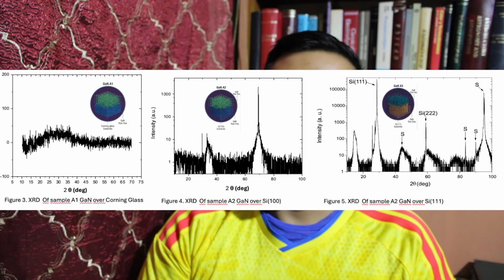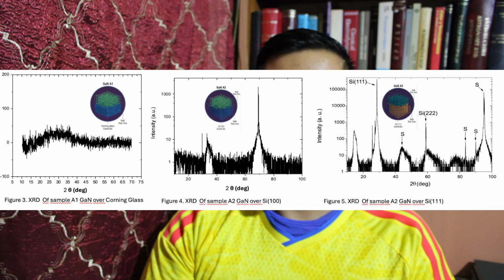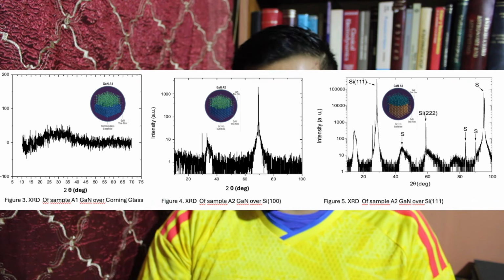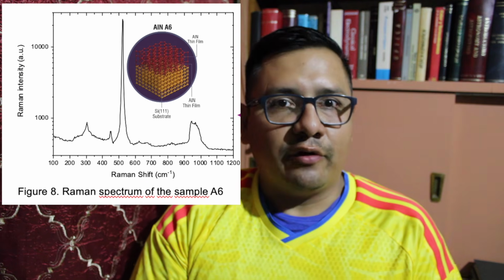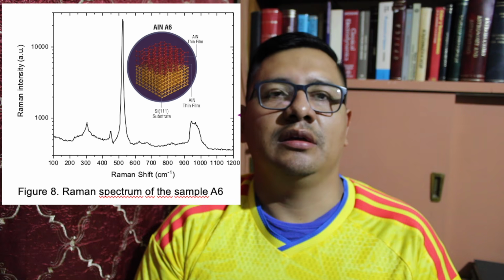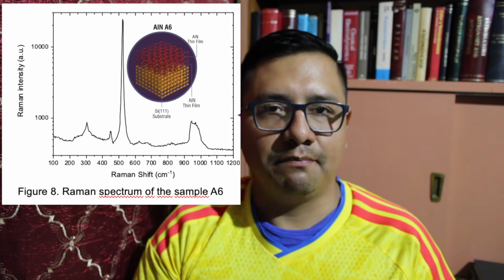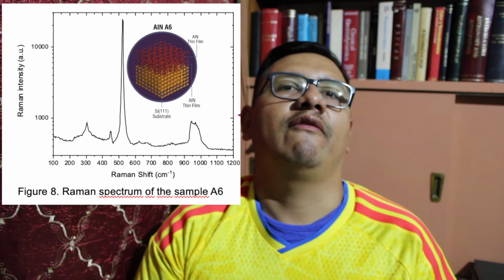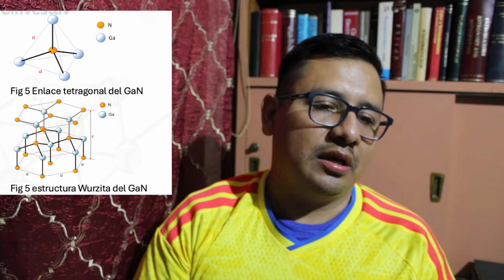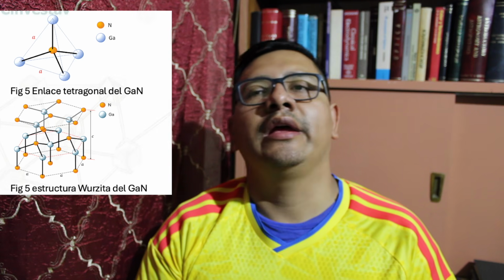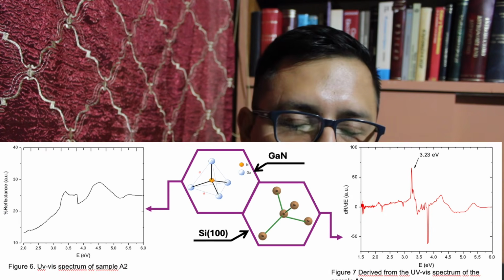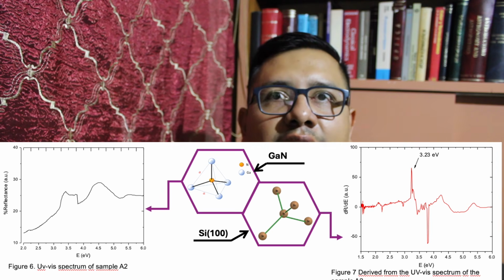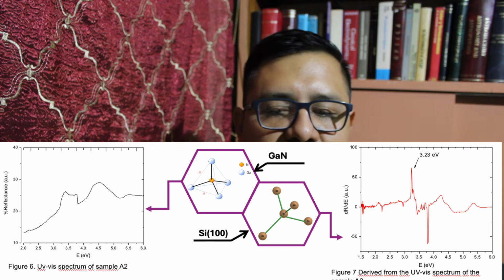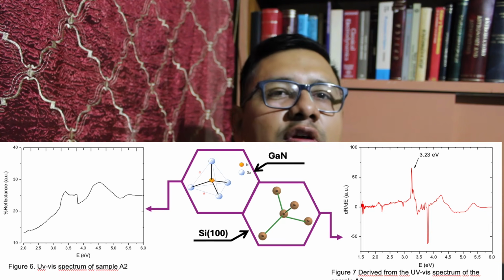In the results, we have obtained X-ray diffraction spectrum and Raman spectrum, where unfortunately we haven't completely demonstrated the presence of gallium nitride either in the cubic zincblende structure or the wurtzite hexagonal structure, but the UV visible spectrum has shown that we have found remnants of the presence of a structure of the gallium nitride.